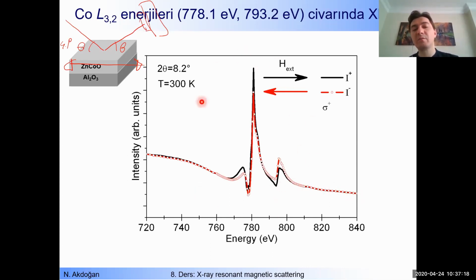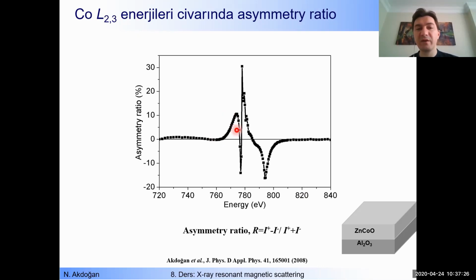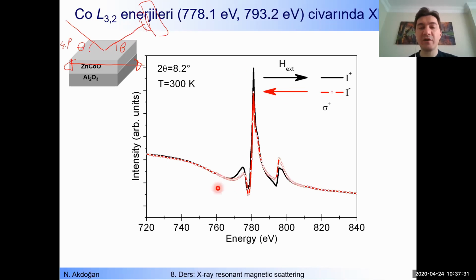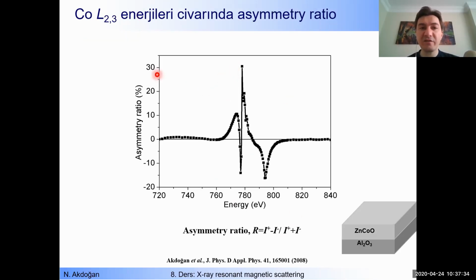But between the energies of L2 and L3 for the cobalt, or within that range, what do you see here? That we have huge difference between two curves, and this difference reaches to more or less 30%. Here it goes to more or less 18%, something like this. So we have huge difference between two curves. So it means that cobalt is magnetic here. This gives us magnetic information about the cobalt.